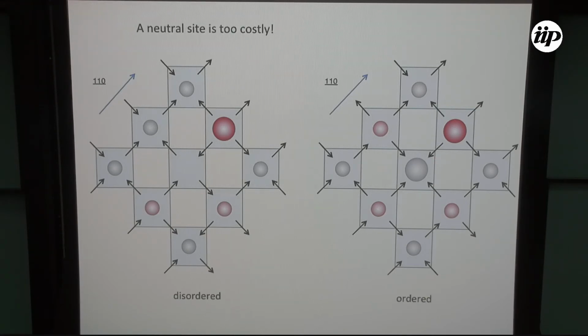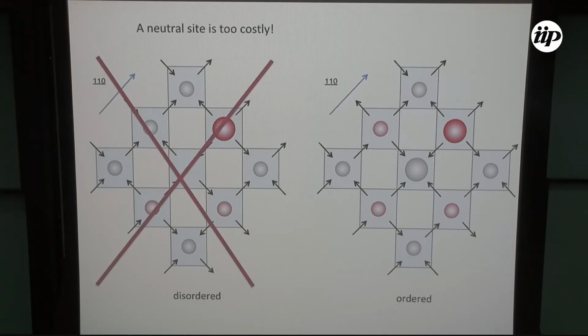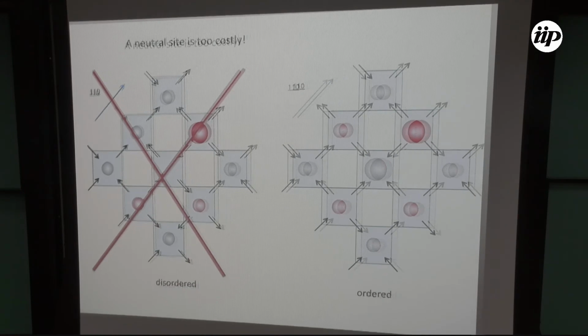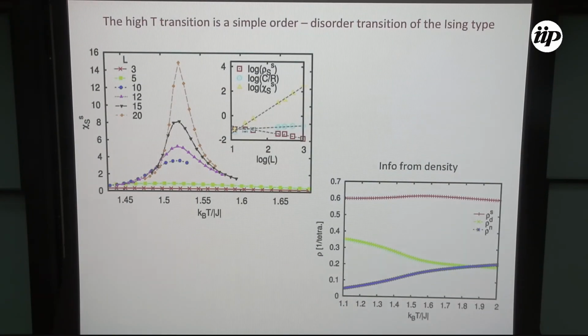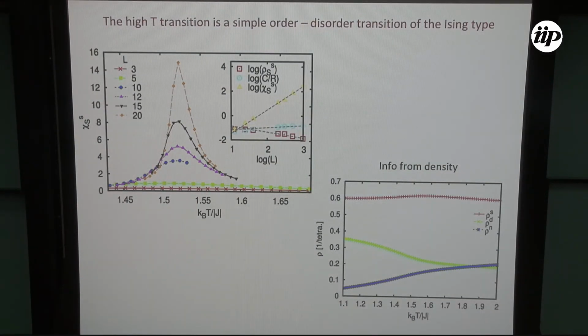And as you remember, the excitations closest to the single charge were the double charges. The neutral site cost you a lot. So this type of excitation would not be allowed at low temperatures, but this type of excitation would be allowed. So you see that if you start from an ordered system, it's a lot easier to get excitations than if you start from a disordered system. So as soon as you put in a little amount of temperature, the system tends to order in charge. So you get this charge ordering.